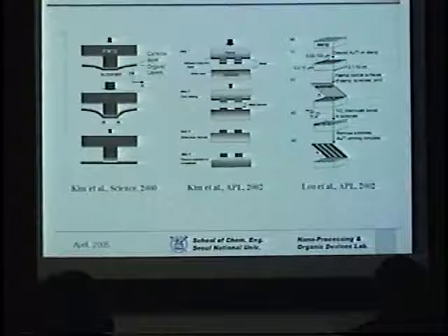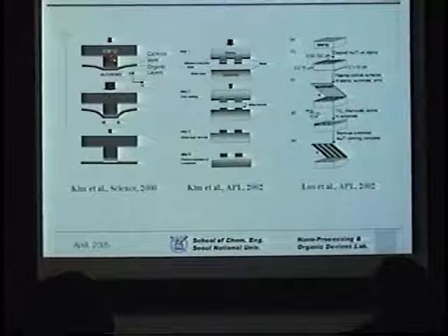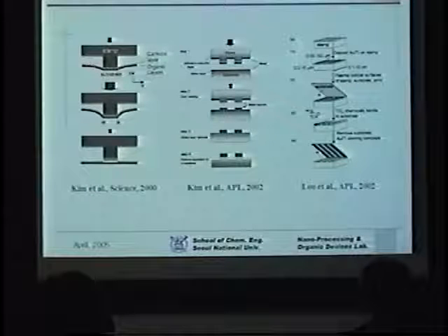Just looking back at what people have done to cope with this problem, we can go to the Forrest Group at Princeton. He came up with what is called the cold welding method. In this case, you have a stamp and you deposit the metal layer onto it. And on the substrate, you also have a metal layer deposited. You press it, then heat it up and remove the mold. Upon removing, of course, it takes the part in contact along with it. So you have the patterning done here.